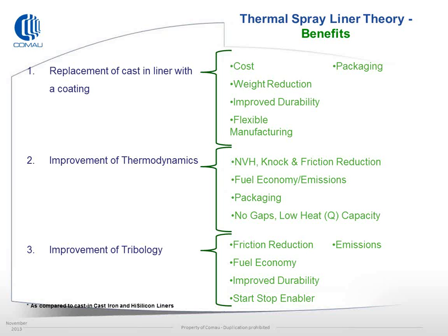Weight reduction, because we're able to package with a smaller liner versus a large cast-in liner, you're able to reduce the length of the block, which has several intrinsic values, reducing the overall length of the engine. Improved durability, we are talking about replacing cast iron with a graphite phase with a hardened steel with inherent porosity that allows us to reduce the friction, but also as well as reduce the wear on the surface.